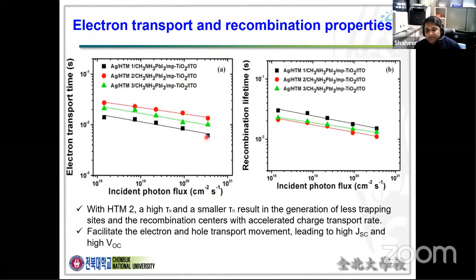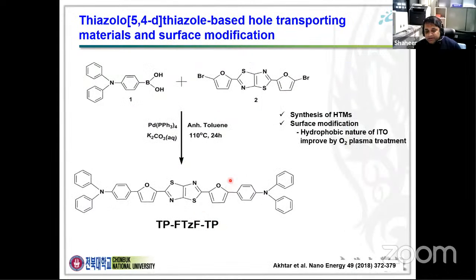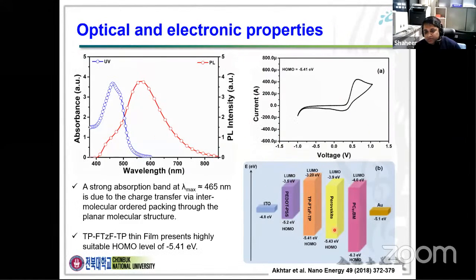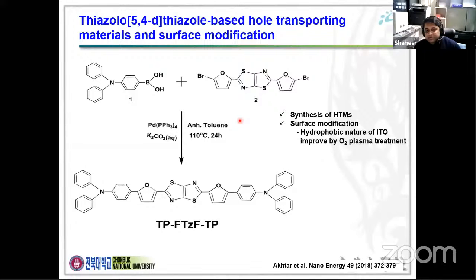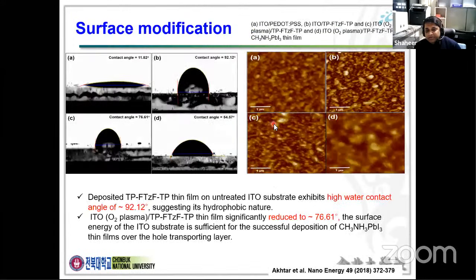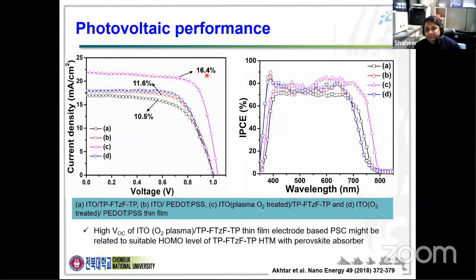The main reason for the improved performance in this case is that it shows a high electron transport rate, and it also lowers the recombination lifetime of the electron. Because of that, it improved the JSC and VOC. Also, we recently published one paper based on thiazole, in which we use triphenyl moieties. The alignment with the perovskite HOMO level is perfectly matched, and the performance is around 16.4%.